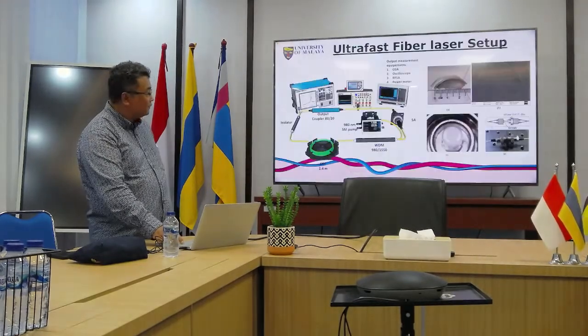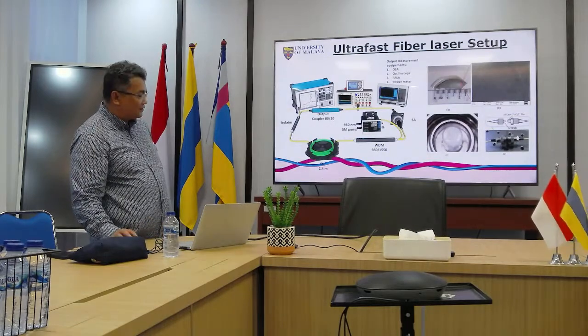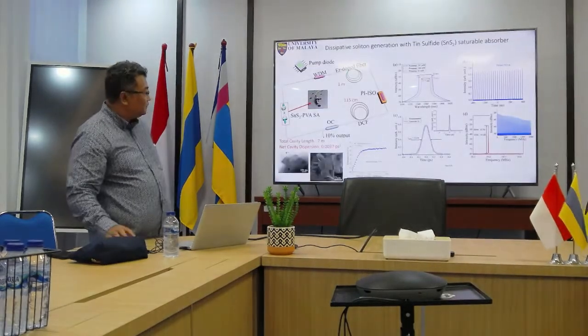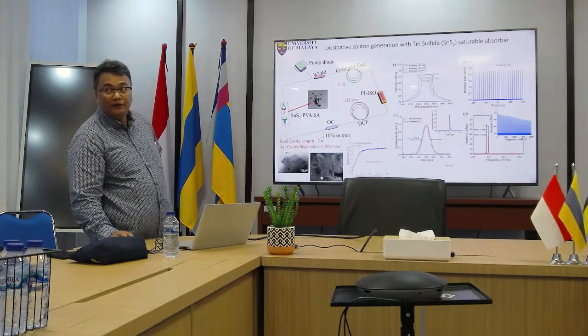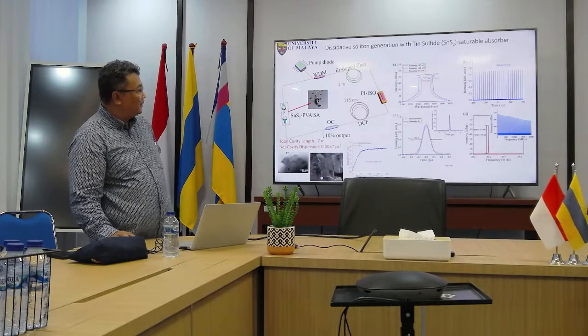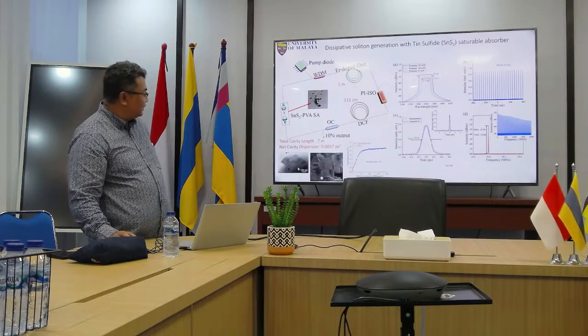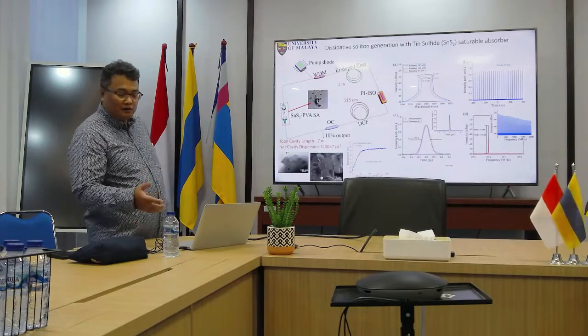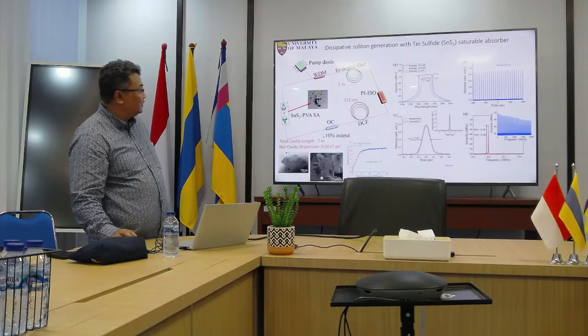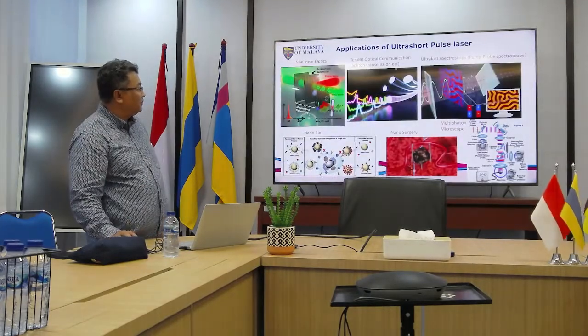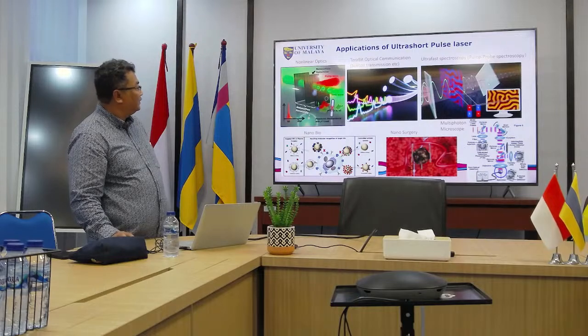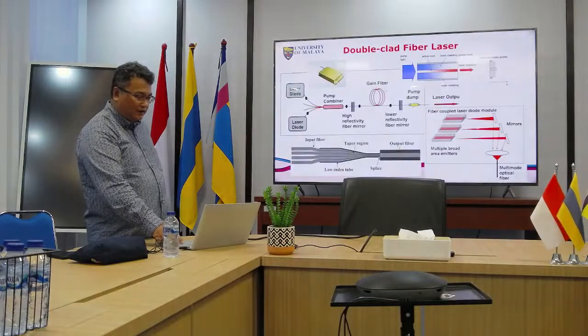This is our pulse laser. We put it in the laser cavity, a ring cavity, and then you can get the pulse here, a 152 femtosecond laser using the fiber laser. This is in the wavelength domain, this is the time domain, and you measure the pulse duration. We use various nanomaterials here as optical components to modulate the laser cavity to generate pulses. This pulse laser has many applications in nanosurgery, microscopy, spectroscopy, communications. It's a lot of applications, and high power.